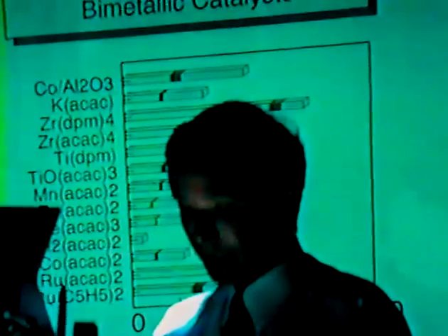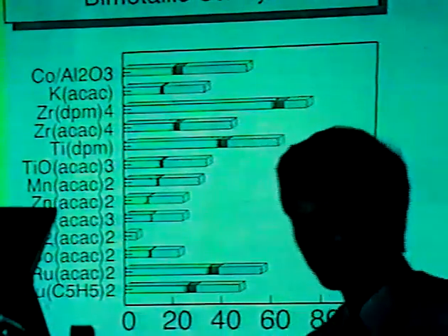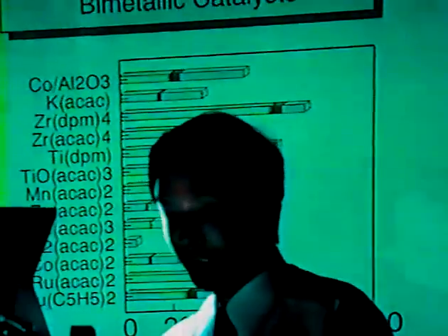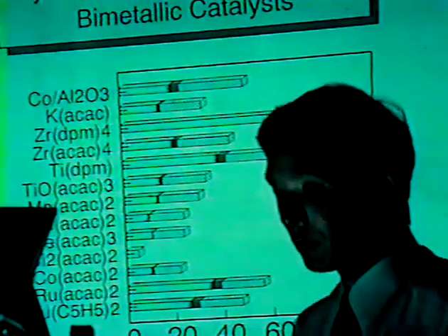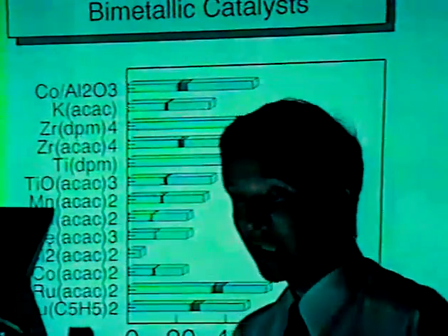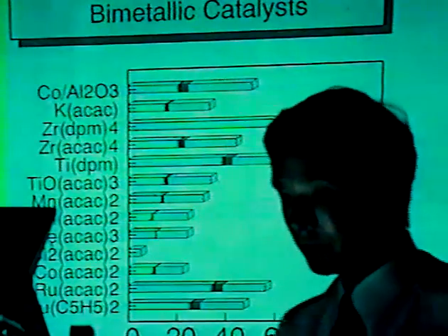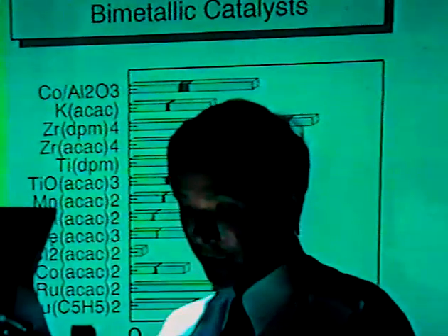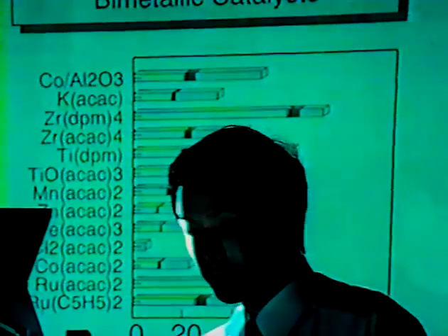Among these, zirconium, titanium, and ruthenium showed a good promotion effect, especially by addition of zirconium compound. The formation of byproducts was only 1/3 of the original cobalt alumina catalyst, and the yield of crotyl alcohol was 3 times that of cobalt alumina catalyst. Similarly, by addition of titanium and ruthenium, the yield of crotyl alcohol increased very remarkably.